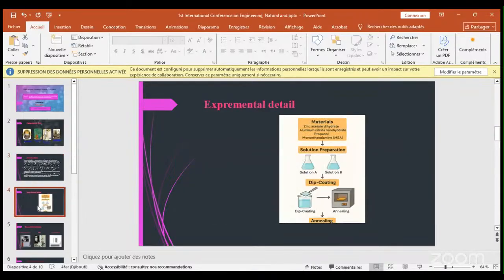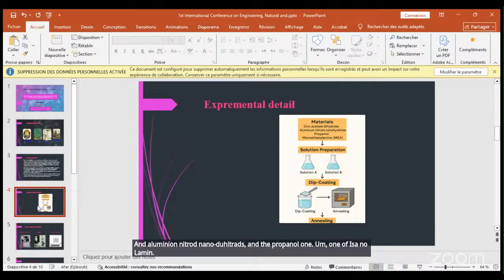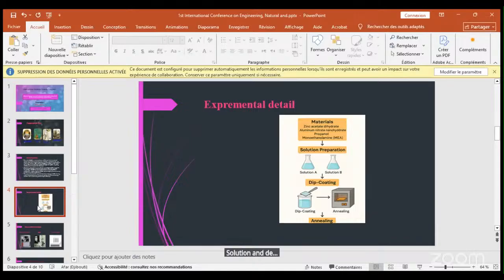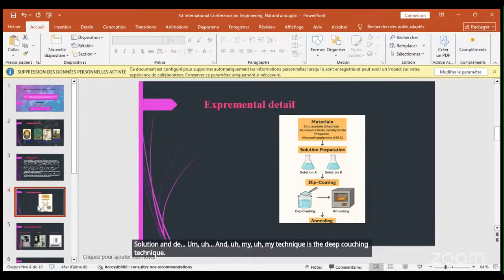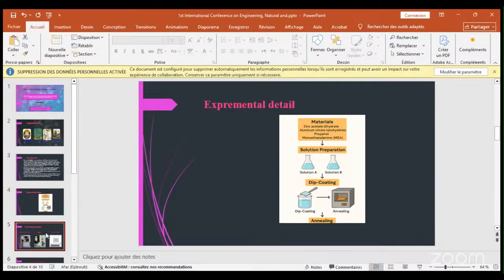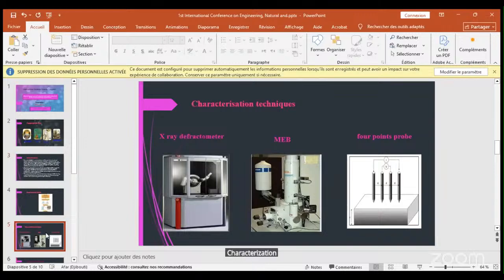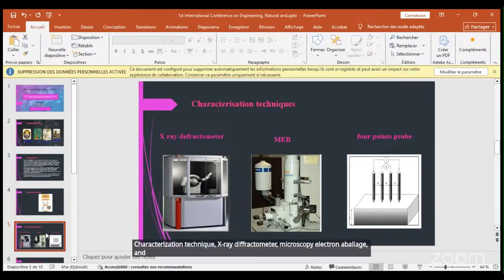This is my experimental detail. The source of materials: zinc acetate dihydrate, aluminum nitrate nonahydrate, propanol-1, and monoethanolamine, solution A and B. My technique is the dip coating technique. Characterization techniques: X-ray diffractometer, scanning electron microscopy, and four-point probe.